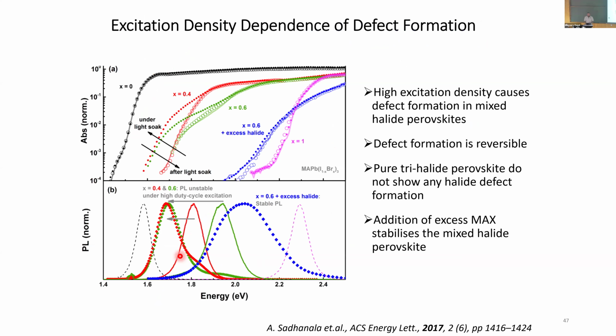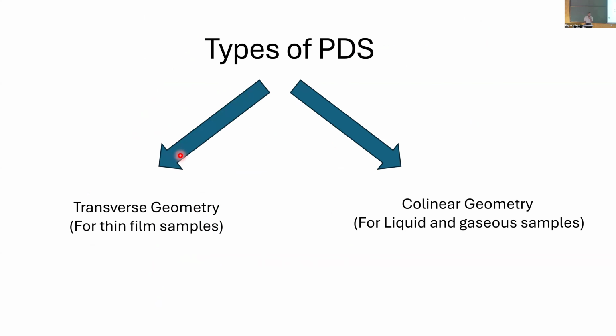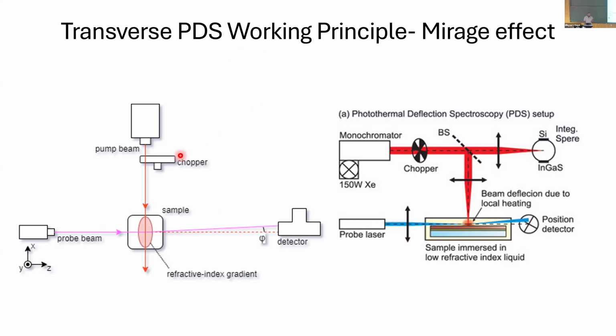I have some perovskite results where I see dynamic absorption shifts, where basically you shine light. This is a halide segregation effect that you have. And coming to a recent interest of mine, what you saw now as a PDS is a transverse PDS. My light was coming in this direction, my probe is going this direction, so it's called transverse. There's a 90-degree angle associated. But in this scenario, I cannot measure liquid samples. I can only measure solid samples.